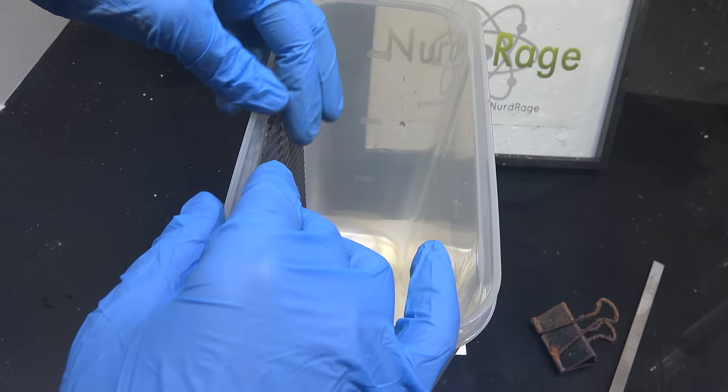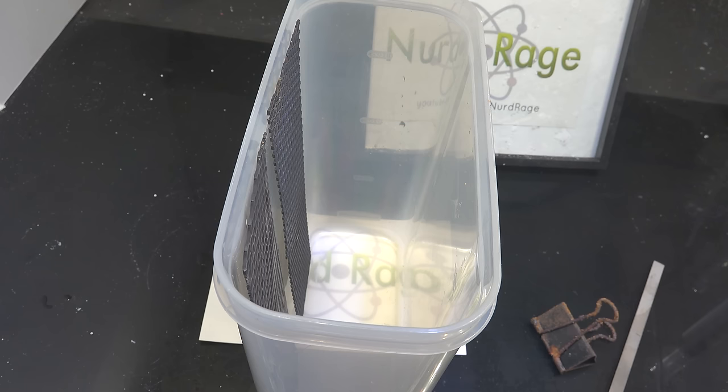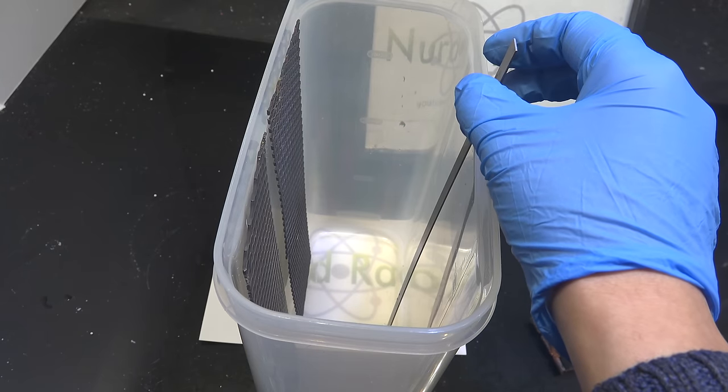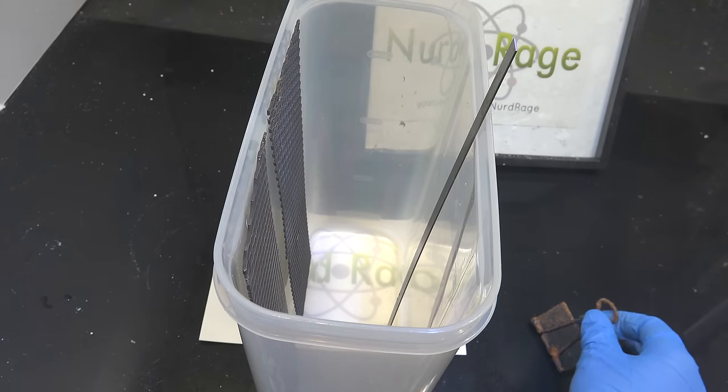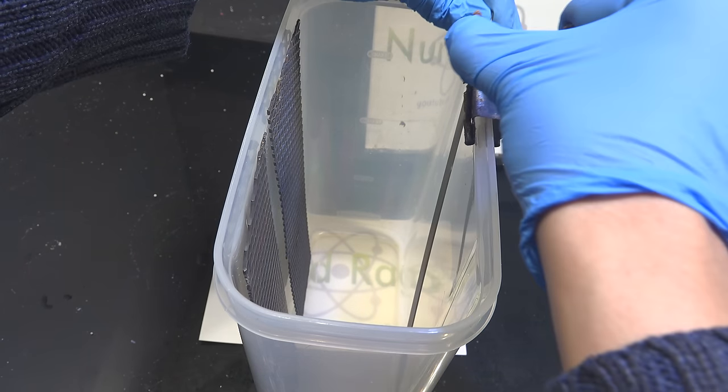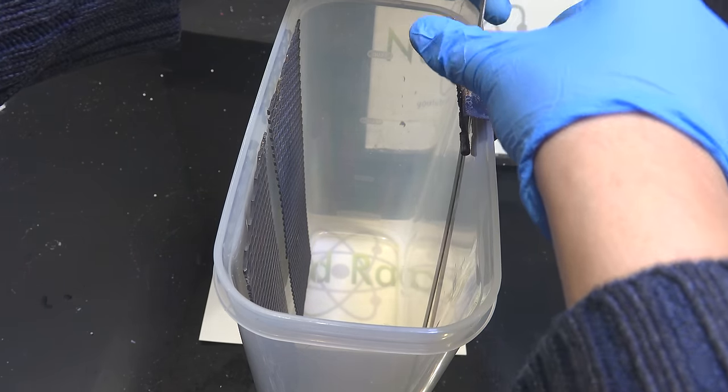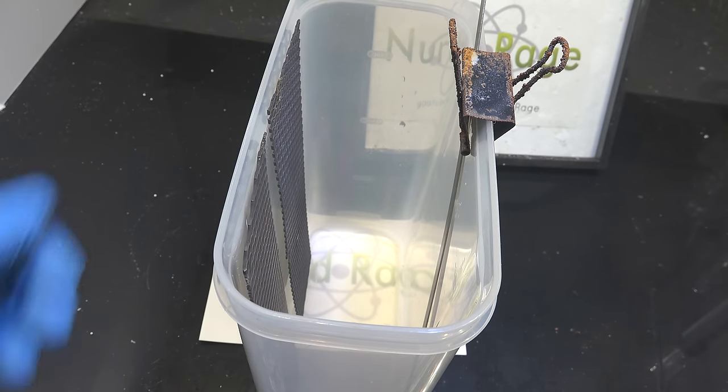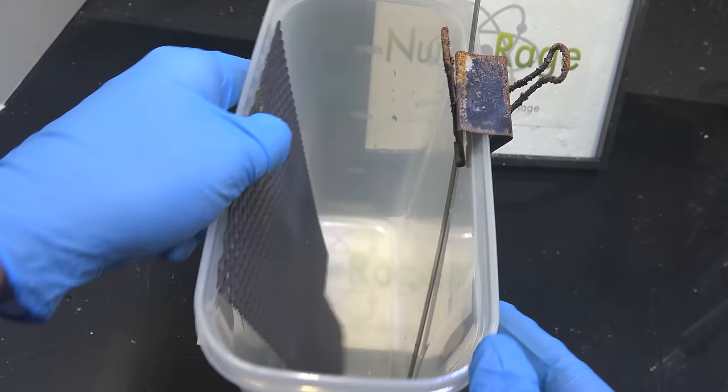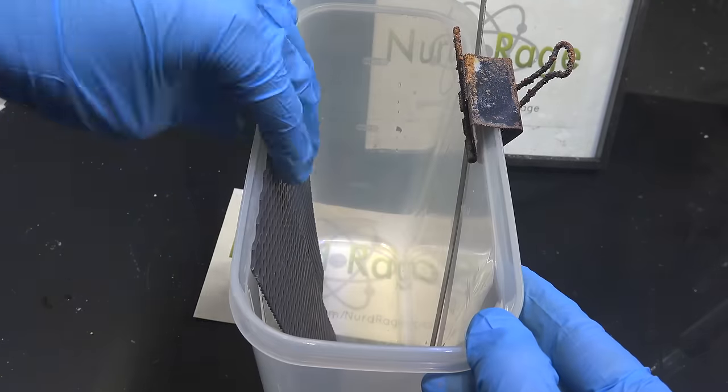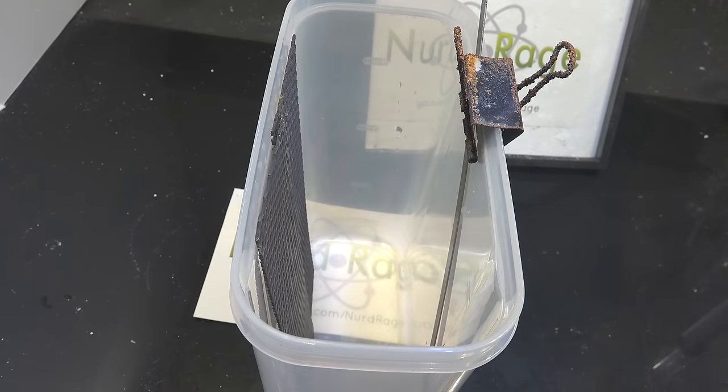Now we're just placing the electrodes. I'm using mixed metal oxide for my anode and for my cathode I'm using a single strip of titanium. You can also use stainless steel or iron but those tend to reduce the chlorates back into chloride so titanium is better. Copper is also less than optimal. I'm using such a thin and narrow electrode to encourage hydrogen formation and discourage chlorate reduction. A mesh is better but I didn't have one. Generally you want a large surface area for the anode and a small surface area for your cathode.